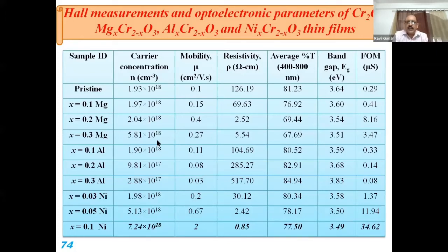Now, if you look at the overall table, I can minimize this. Here, the last column is the figure of merit, which depends on the transparency, conductivity, Hall mobility, and so on. The figure of merit clearly tells us that magnesium will have a figure of merit of 8.16, and nickel will be 34.62. That will give the quality of the device, if at all.